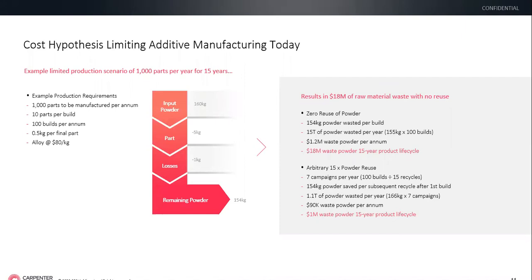So what happens is if you essentially are not recycling and reusing the powder, it leads to an additional material cost of about $18 million. You're essentially wasting 154 kgs of powder per build because you're not recycling, which means you're wasting about 15 tons of powder per year and about $1.2 million of powder per year, if you translate that into cost. For titanium, the cost is going to be higher, so the numbers are going to be significantly higher.